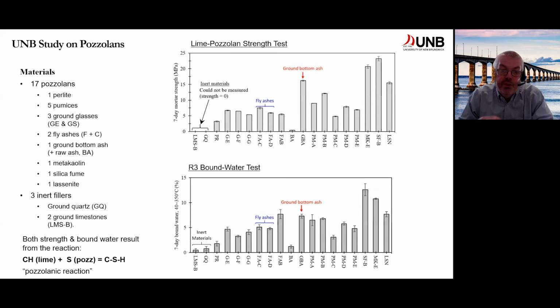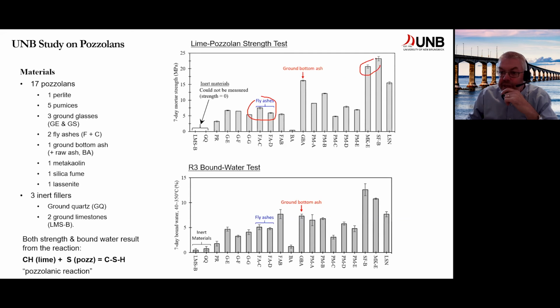So I'm showing some data here. I'm not sure if the pointer works here or not, so I'll turn on the pen here. The top graph shows the 7-day strength of mortars. These are lime pozzolan mortars. You can see for the range of materials here, we're getting very different strengths between fly ash here and metakaolin here. But the test really is capable of distinguishing between inert materials and reactive materials. If you have an inert material, you get no strength whatsoever.